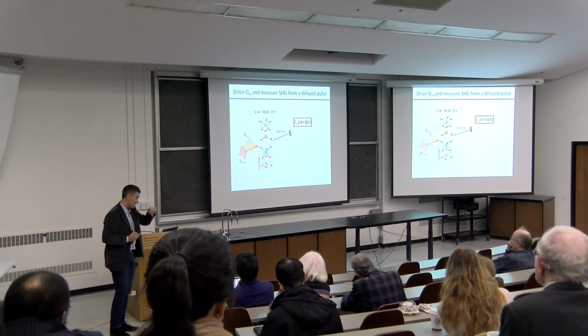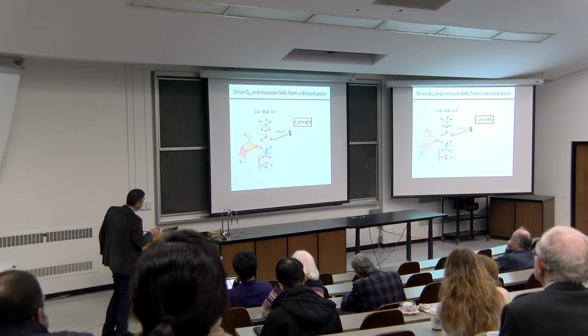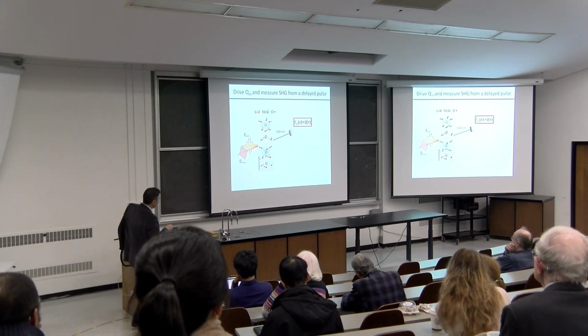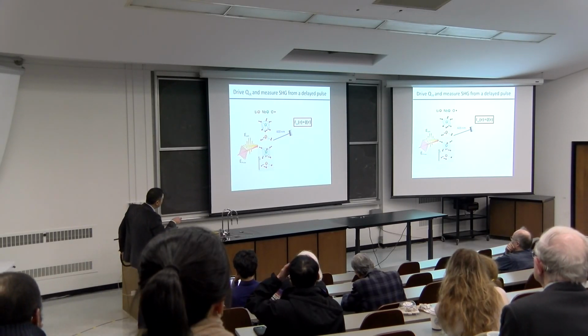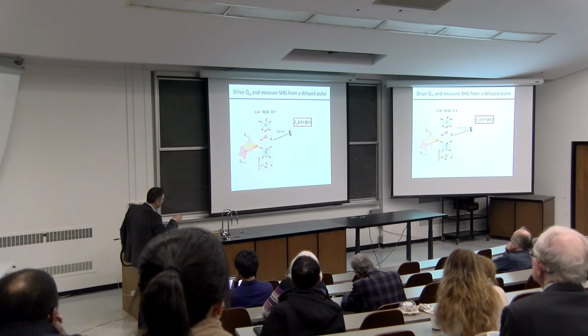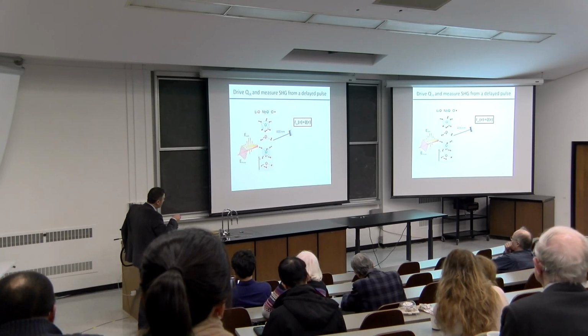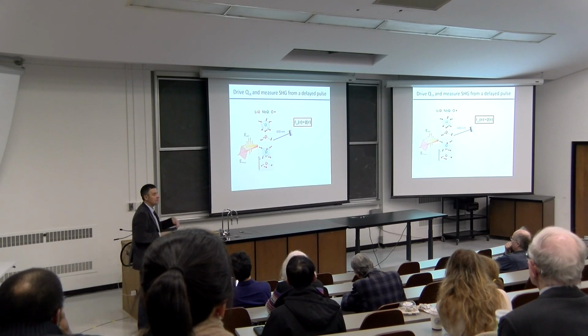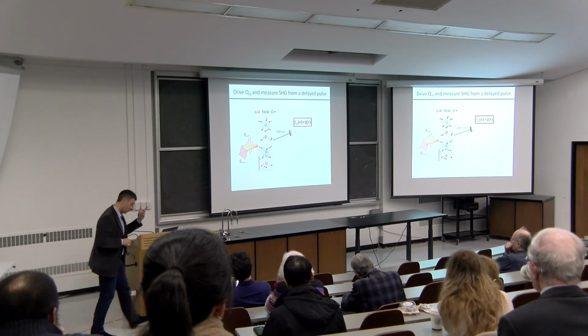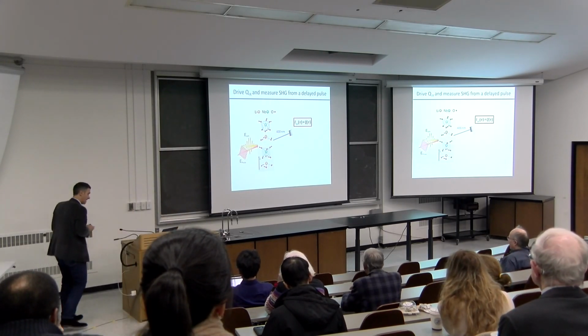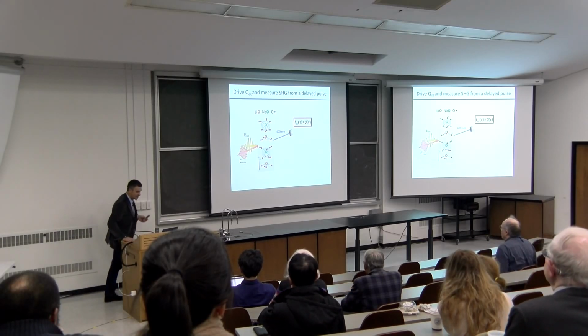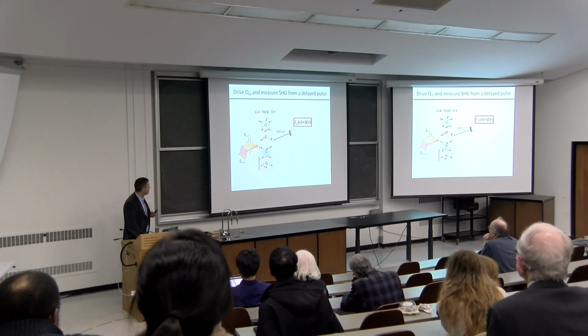following my drive, okay? And for various reasons that I won't belabor, the way this experiment gives you a signal, which is the second harmonic of the probe, is not proportional to the coordinate of the phonon, but it's proportional to its derivative. It has to do with the fact that I have a time-dependent nonlinear tensor, which then basically gives me the velocity of the phonon.